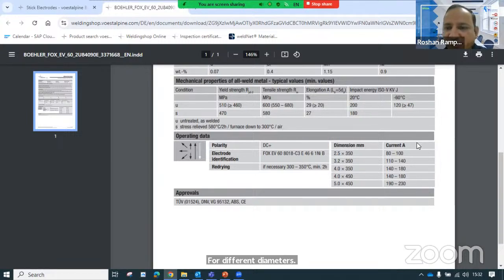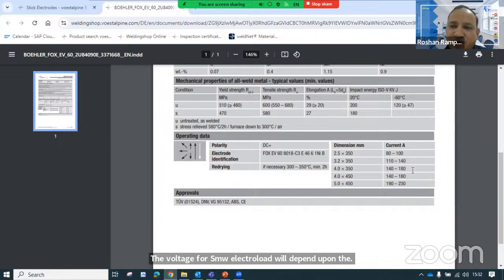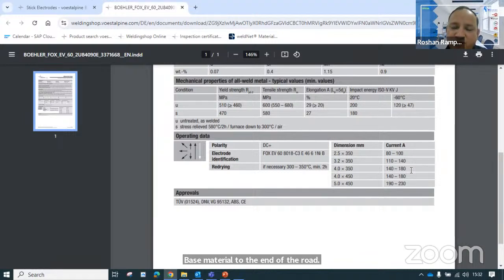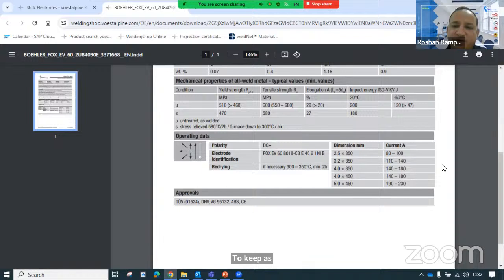Voltage is not mentioned here because the voltage for an SMAW electrode will depend upon the arc length, or we can say the stick out, the distance from the base material to the end of the electrode. If it is too high, then the voltage will be higher. It is a constant current type of process, and voltage is always fluctuating, so you keep the electrode tip as close to the base material as possible. You qualify the procedure by doing the testing. If it meets the requirement, then prepare a WPS within those qualified parameters so that it will give you similar results in the actual fabrication also.